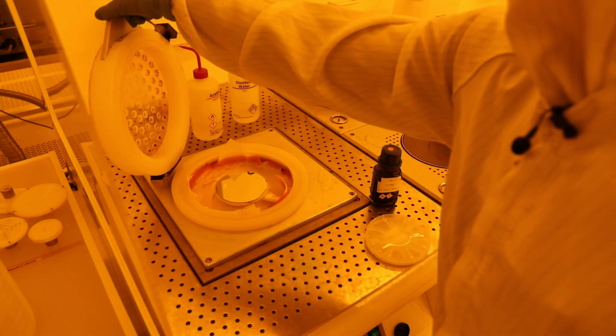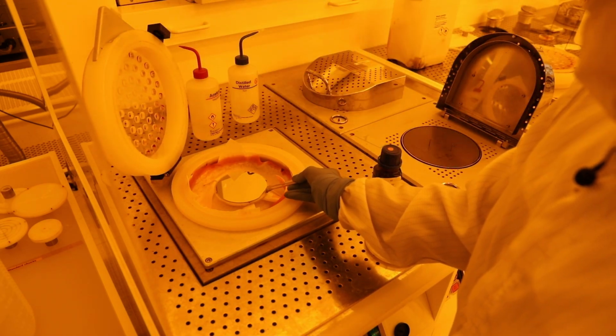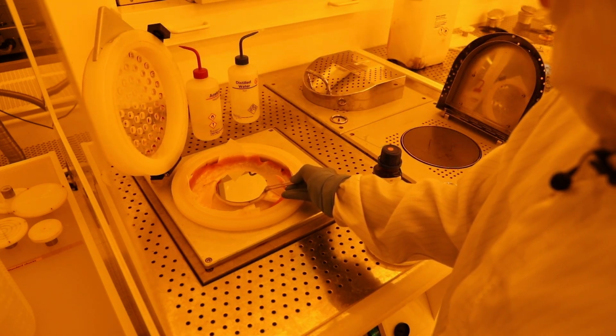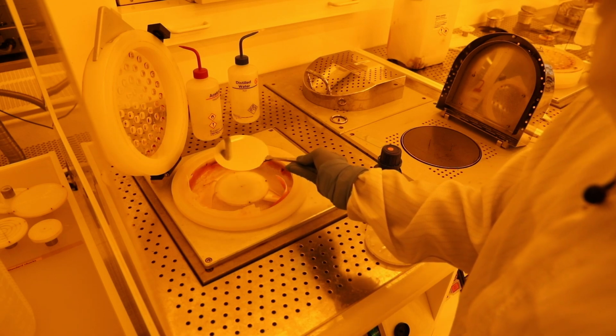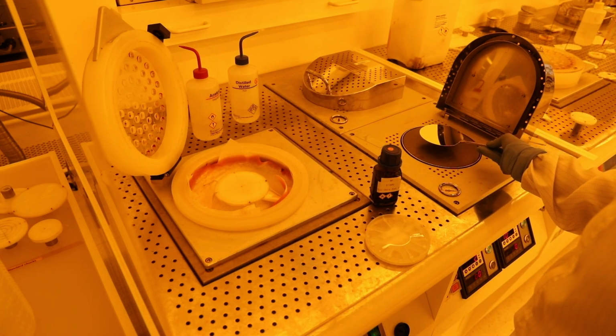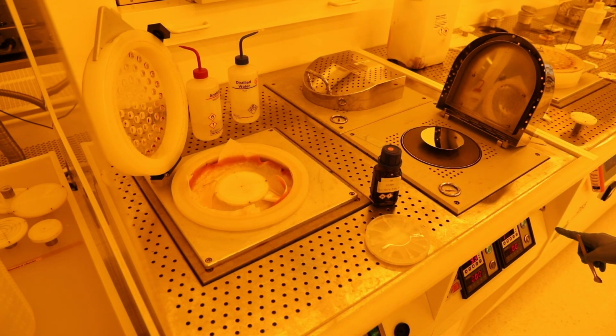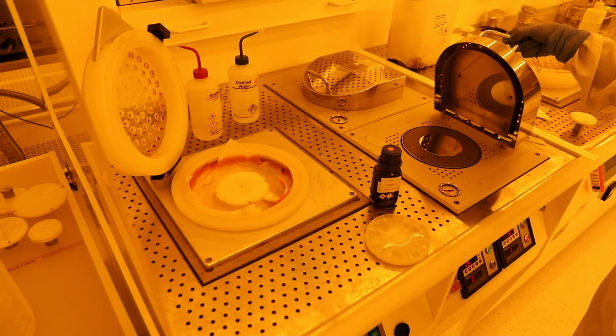After spinning, we should have about half a micrometer of resist covering the wafer, with the excess liquid having been flung off the surface towards the edges of the spinner. I will shortly bake the resist on a hot plate to evaporate any residual solvent, solidifying the liquid into a thin layer into which we can expose our pattern.